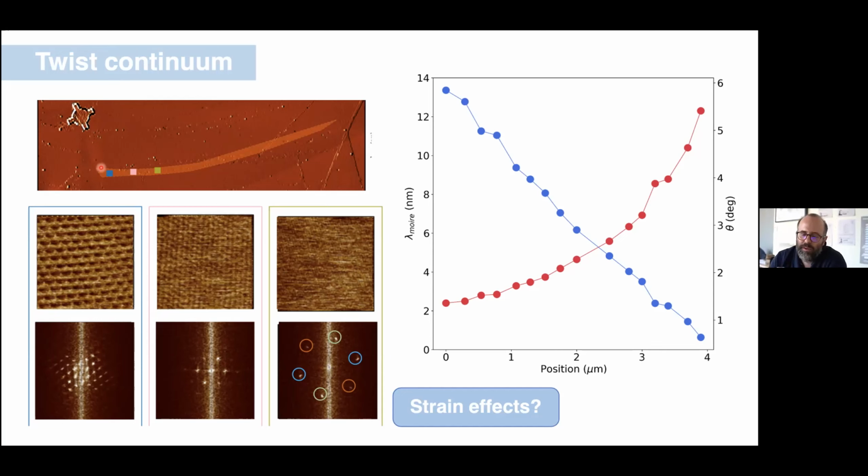A Hall bar is not the best way to measure the presence of Landau levels in this system, because you actually expect counterpropagating edge modes, since the strain gauge field couples to the K and K prime valleys in opposite senses. So we have also started the process of measuring Corbino response by imposing a dot array inside one of these bent noodles. That data is too early to say anything meaningful about. What I do know is that the transport is absolutely varying as you move through the system, but we're not yet clear whether we're measuring something that really is emergent Landau levels or not.